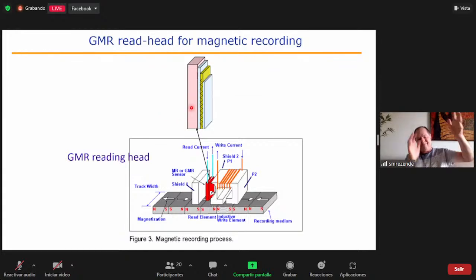we can put this in the sensing layer of a magnetic recording medium. What is the advantage of this? The advantage is that traditional conventional recording used as detection the Faraday effect. Now, the Faraday effect requires flux to induce a voltage. And flux requires area, volume. So magnetic recording conventional reading had a problem with that. The bit for magnetic recorder had to be large because the flux had to be large.